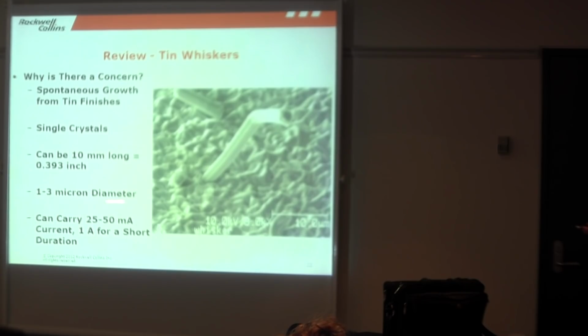The diameter is pretty consistent. They're all between 1 and 3 microns. They don't really get much bigger than that. That's one of the few constants if you look at how a whisker grows. Again, they're single crystal. And after they grow so long, I think it's a 17-degree angle. But there's a specific angle a lot of them bend to. And it's part of their crystallography as they grow. But they grow right out of the base. They don't grow by adding atoms up here. And they grow from grabbing tin atoms throughout this whole area.